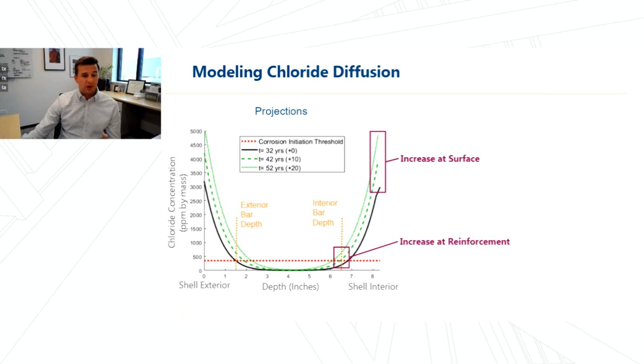There's also an increase in chloride concentrations at the reinforcement. And this makes sense for 2 reasons. One, we're increasing the total chlorides in the structure, in the system. And 2, over time, diffusion is going to continue and diffuse towards the center from the high concentration and high exposure at the surface. So now we can also use these tools to evaluate repairs.